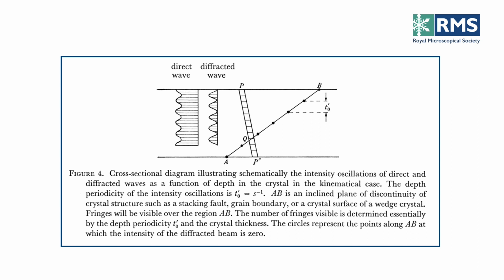If you are at the Bragg diffraction, you get a diffracted beam. The intensity oscillates with depth, and that's also reflected in the direct wave, of course, correspondingly. And if you now have a line like AB, if you think of that as a line lying across, and you're looking by this column approximation along the diffracted beam direction, you get oscillating contrast, and at certain points where the diffracted beam is actually zero, you will see nothing, at least no change. And so you get oscillating contrast, which is what he saw.